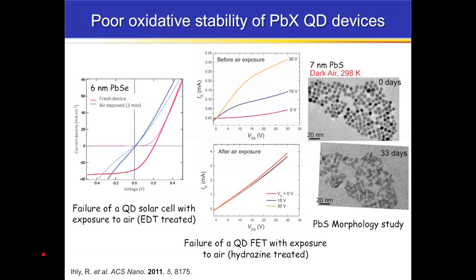So I'll show you here some data on the poor oxidative stability of lead salt, where by salt I mean telluride, selenide, or sulfide dots. This shows a solar cell here before air exposure in red and after a very brief air exposure in blue. You just totally lose the diode. This is a field effect transistor before air exposure and after air exposure, and it's not important that we understand the details here, but you can see that you get a large change in behavior. That's not good. This was a hydrazine-treated device. That was an EDT-treated device.